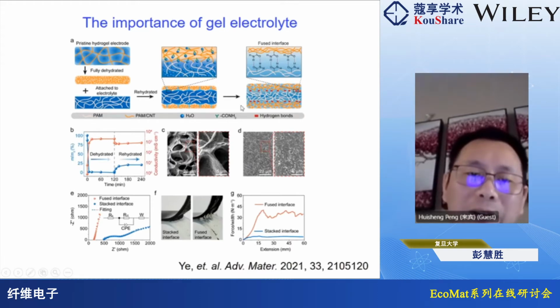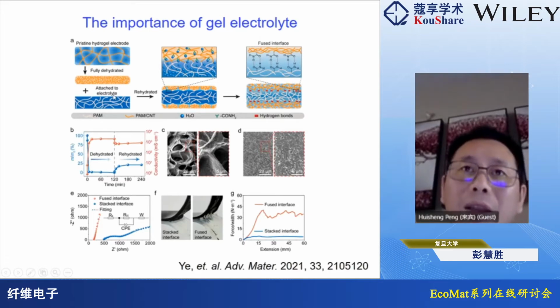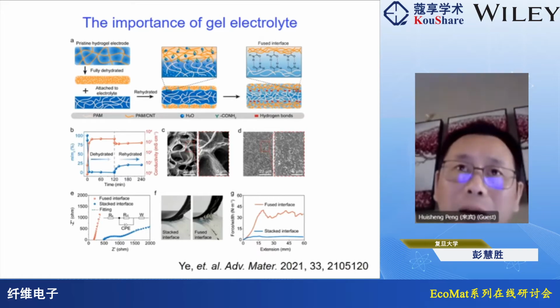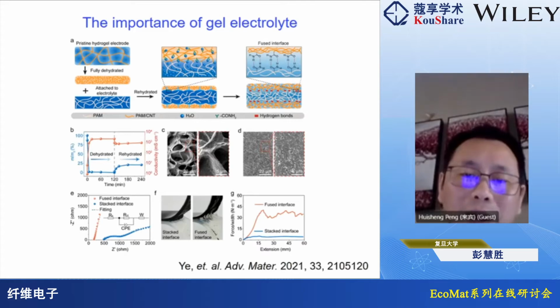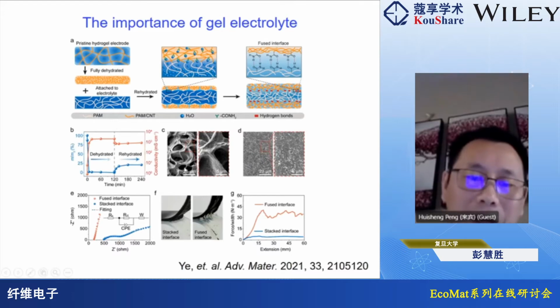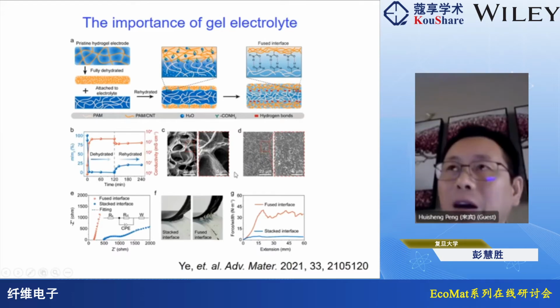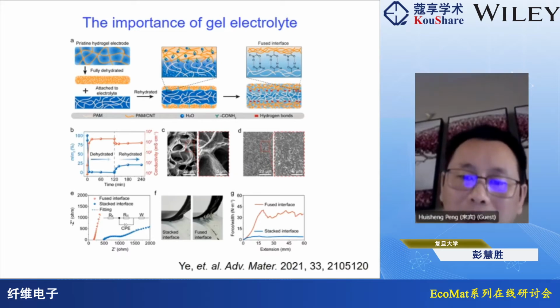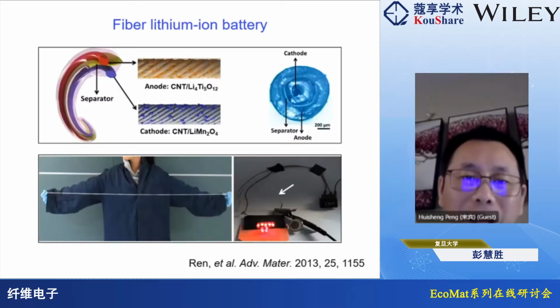Then we found a very effective solution to this problem. We first designed monomers, and the monomers are liquid and can infiltrate into the fiber electrode and also into the batteries. And then after in-situ polymerization, they form polymer gel electrolyte, and then we have this semi-solid fiber battery.